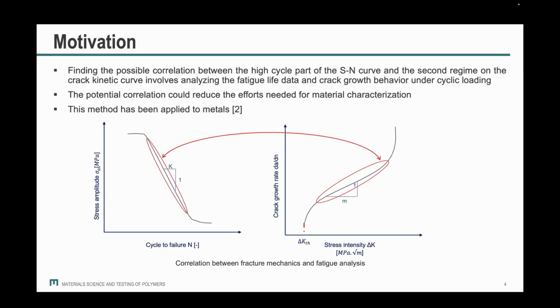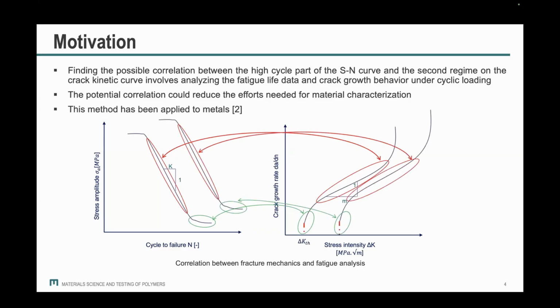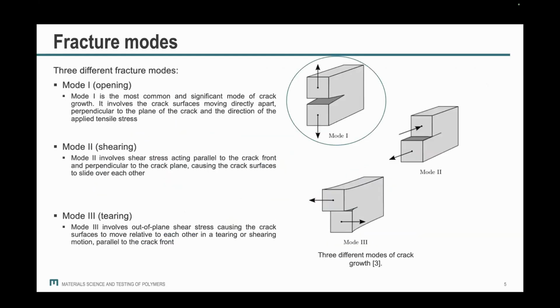And we know the fact that during the production, we have always some defects in the material. And in the literature, they use two different approaches to find the correlation between crack initiation part on the crack kinetic curve and the very high cycle fatigue regime on the SN curve, and to find also the correlation between the second regime on the crack kinetic curve, also where we have a stable crack growing in the component, and the high cycle fatigue regime on the SN curves. For this study, we use just the first fracture mode, also just opening.